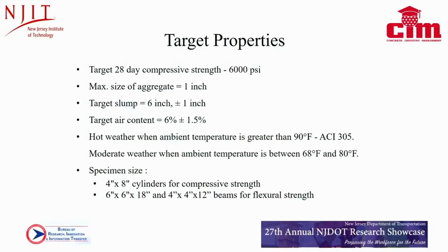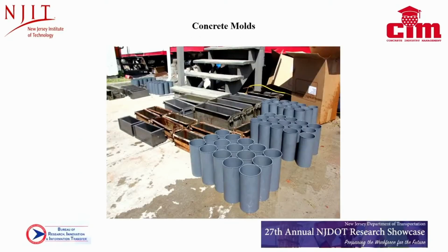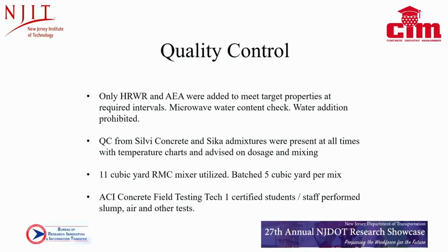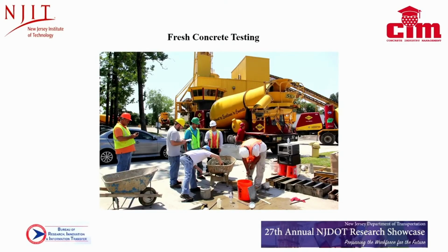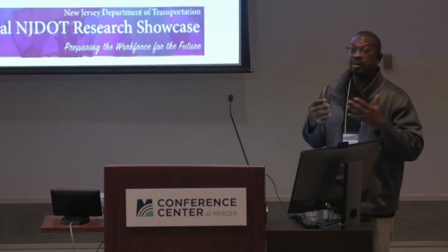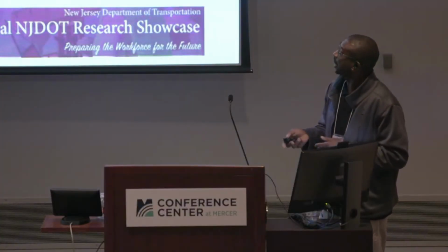All right, so here we have pretty much the targets: maximum aggregate size of 1 inch, slump target of 6 inches, air content, and the temperature that we're working with. We also did mixes during the summer and during the fall to get different results and see the effect the environment would have on the concrete. So here we have pictures of our molds, pictures of tests being done. That's the concrete truck in the back with the actual concrete. So again, we decided to do it on a large scale so that it replicates actual mixing in the field.